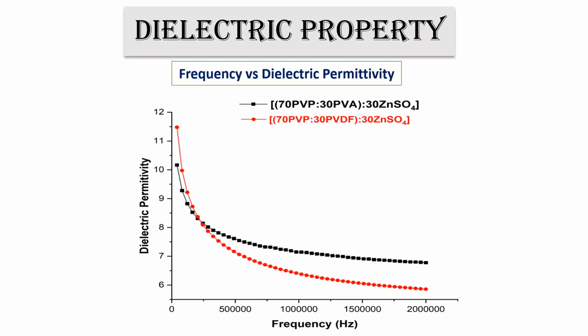Dielectric permittivity is also very important when we say these materials are useful for energy storage devices or supercapacitors. So here the frequency again goes up to 2 megahertz. Both samples show good agreement in the low frequency range. I have analyzed data from 1000 Hz to 2 megahertz.